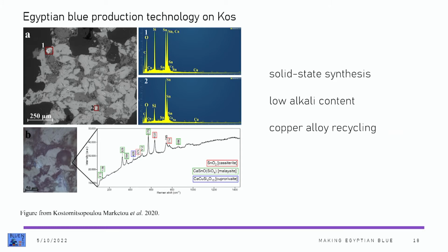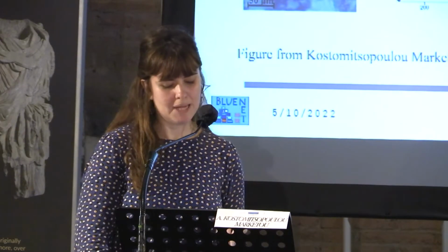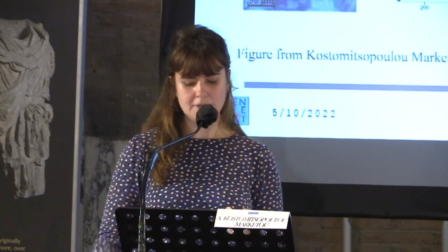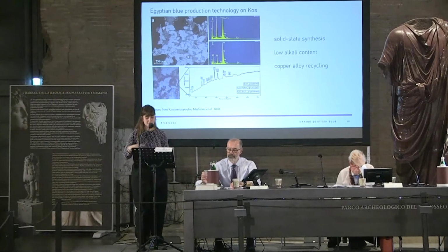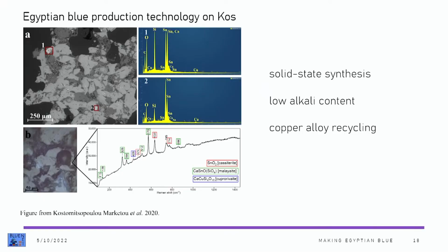Now, the micromorphology, I won't really get into details about this, but I'm happy to share the work that has been published. In short, the micromorphology of the finds demonstrate that we have a low alkali starting mixture and a solid state synthesis. And the detection of tin in the analyzed samples may be indicative of the use of bronze as a copper source, possibly suggesting the recycling of copper alloys to produce Egyptian blue at the site.